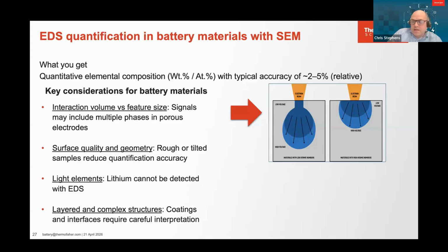So typically one of the techniques that we use is to go down to a lower primary beam energy. That would give you a smaller interaction volume. And we also do quite a lot on the processing side to make sure that the quantification routines can be as accurate and reliable as possible.